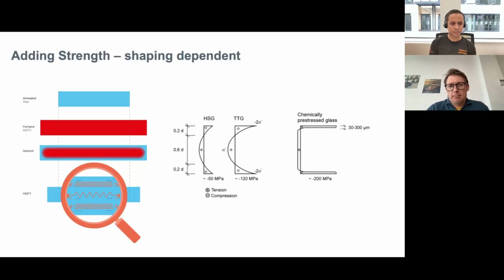And if we look at the stress through the sections of glass, on the right-hand side in the 3 diagrams, we have a heat-strengthened glass and thermally toughened glass. So again, we have about 50 megapascals in the heat-strengthened glass and 120 megapascals in the thermally toughened glass. Finally, there's one other process that we won't really dwell on, and that's a chemical tempering process. That puts a very high stress in the glass, typically 200 megapascals, but it's a very thin compressive crust of 30 to 300 microns. That's used much more in automotive and transport vehicles and trains, for their windshields.